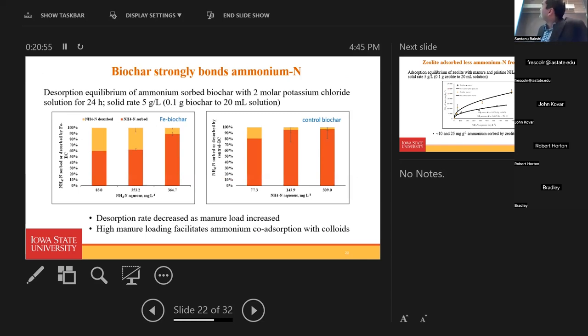In the next slide, we did the desorption from the ammonium-sorbed biochar with 2 molar potassium chloride, 24 hours, and the same loading rate. We found that biochar strongly bonds ammonium nitrogen. Desorption rate decreased as manure load increased, and high manure loading facilitates ammonium co-adsorption with colloids. On the left side is the iron biochar data, and on the right side the control biochar data. The ammonium sorbed is the orange one, and the ammonium desorbed is the yellow one. In the control biochar, most of the ammonium is still in the sorbed condition.